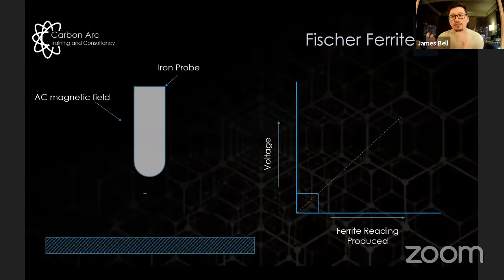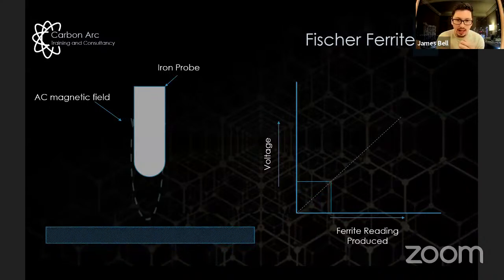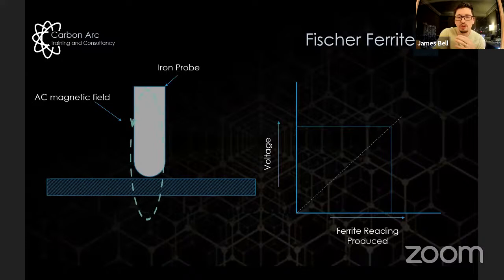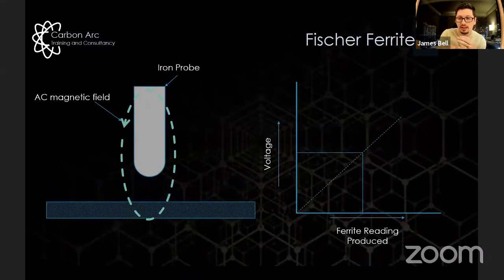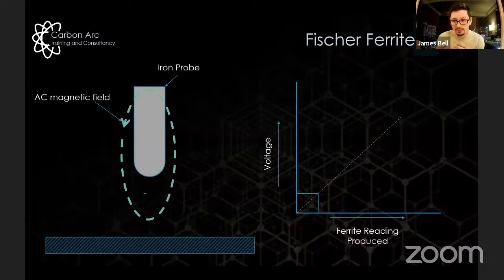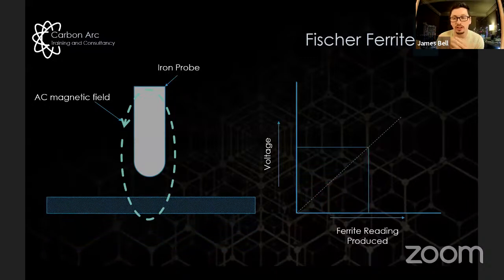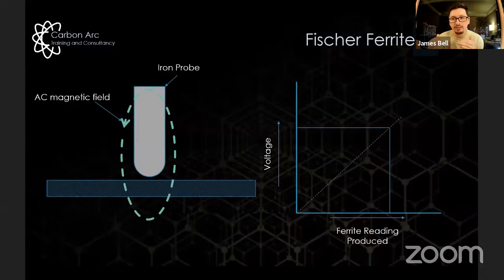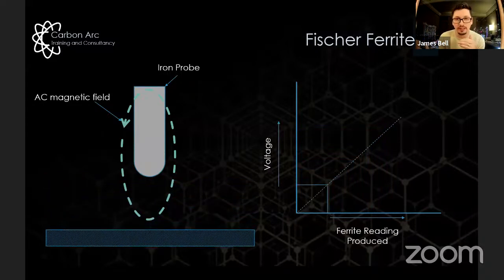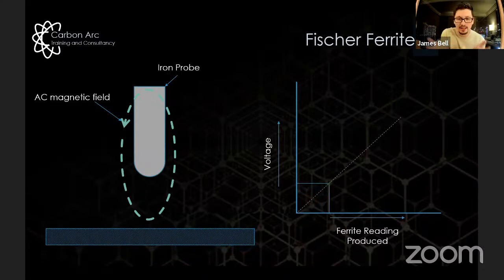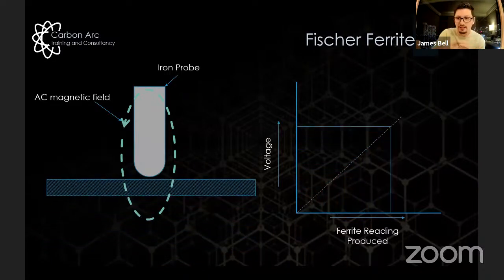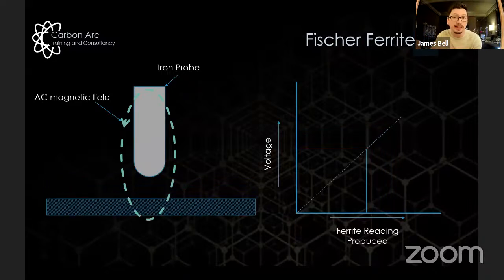Now, the Fischer Feritscopes we were using, if you haven't had very much experience with them, are basically made from an iron probe in a plastic sheath, and they produce a magnetic field. And when the AC magnetic field comes close to the part, the ferrite content within the steel increases the voltage level, and the machine reads that to a corresponding ferrite reading. So you can see here, as the part comes closer, the magnetic field gets larger, the voltage goes up, and the reading then goes up.